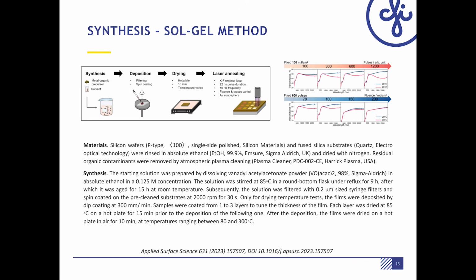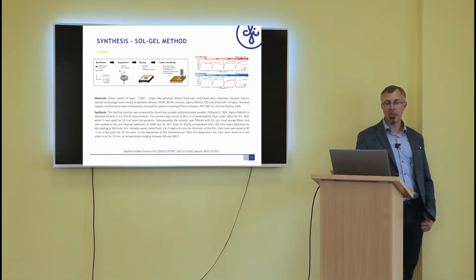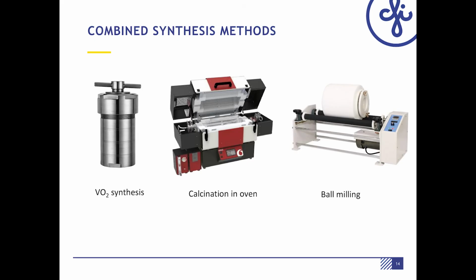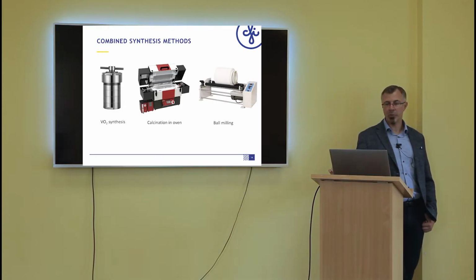To achieve high thermochromic performance, it is necessary to process films. In this case, laser annealing is used, and a combined synthesis method. First of all, nanomaterials are synthesized using hydrothermal method. After that, nanomaterials are calcinated in oven in controlled atmosphere. And after that, ball milling in solution in presence of surfactants is used to achieve a proper size of vanadium dioxide nanoparticles.